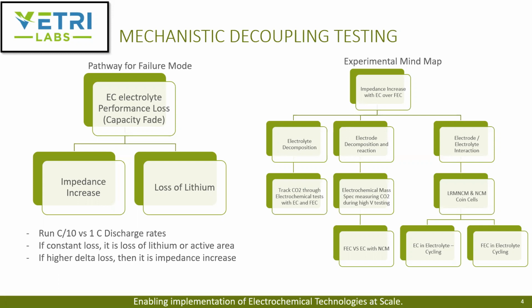For the electrolyte decomposition experiments, they use a separate cell with electrochemical mass spectroscopy, with a carbon working electrode, and the electrolyte system using both ethylene carbonate and fluorinated ethylene carbonate. They take the working electrode to potentials typical of the first activation step of the battery, close to 4.7 volts, and even further to 5 volts, to study differences in carbon dioxide evolution between the two electrolyte systems.